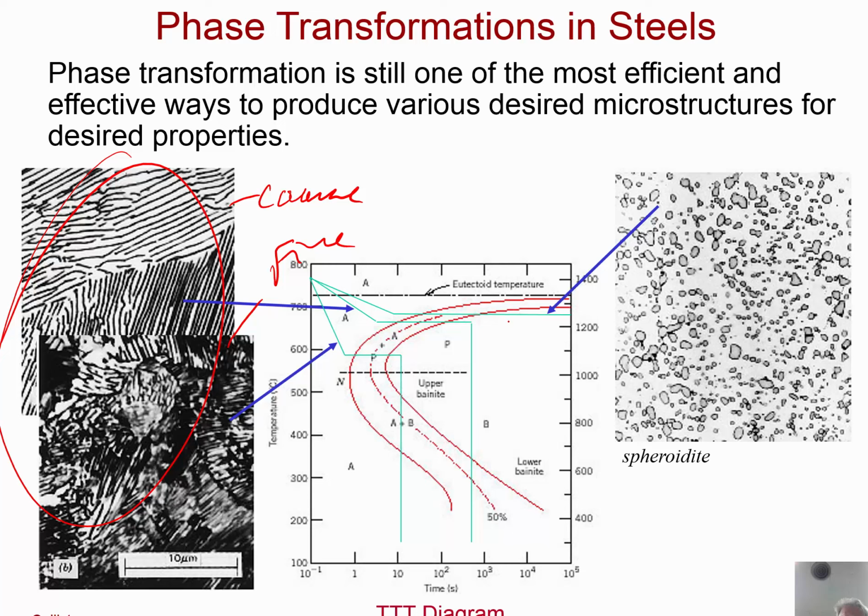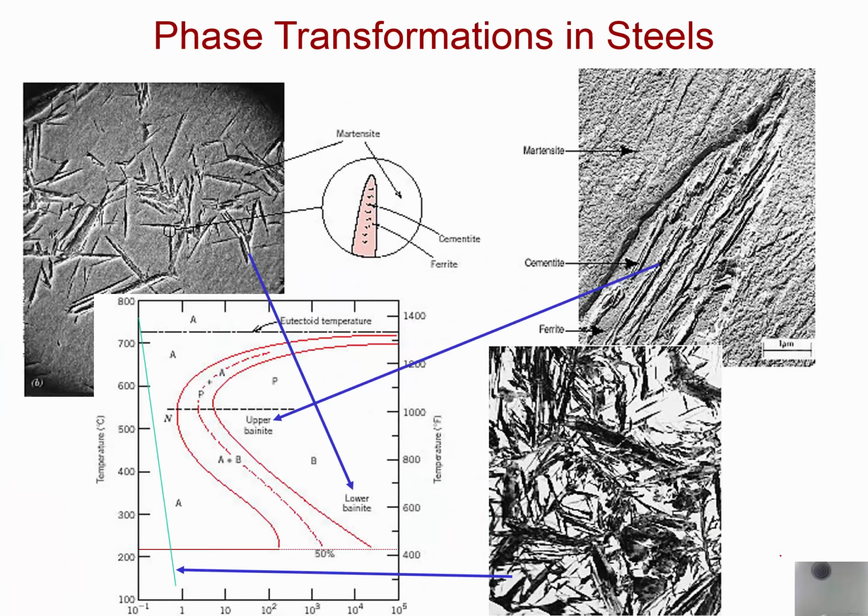And if you take these structures and hold them a long time, they want to decrease their surface energies. And so they form these things called spheroidite. And again, the lamellae end up basically breaking up, and diffusion brings them into spheres to reduce their surface energy. Usually, there's another picture in here that shows sizes. Usually this is on the order of a few microns, which is actually fairly large in the whole scheme of things.